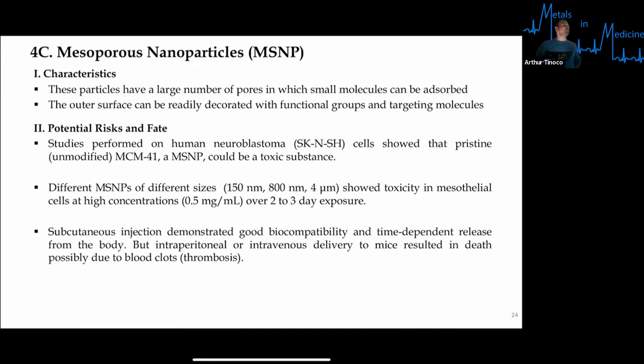So studies performed on the human neuroblastoma cells, SK and SH, show that pristine, unmodified MCM41, which is a mesoporous nanoparticle, could be a toxic substance. So different MSNPs, so mesoporous nanoparticles of different sizes, 150 nanometers all the way to 4 micrometers, show toxicity in mesothelial cells at high concentrations, 0.5 milligrams per milliliter over 2 to 3 day exposure.